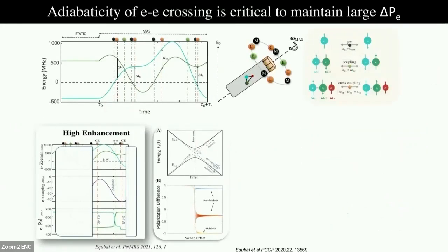And why we want effective electron-electron coupling, strong electron-electron coupling, is not just to maximize the cross effect rate, the CE rate that I showed you in the previous slide. It's rather to maintain a large polarization difference between the two electrons. If we look at these energy pictures of the two electrons, there are points where the two energies of the electrons become the same. At those conditions, if the coupling is weak, then something undesirable will happen, which is that the polarization difference between the two electrons would not be maintained.